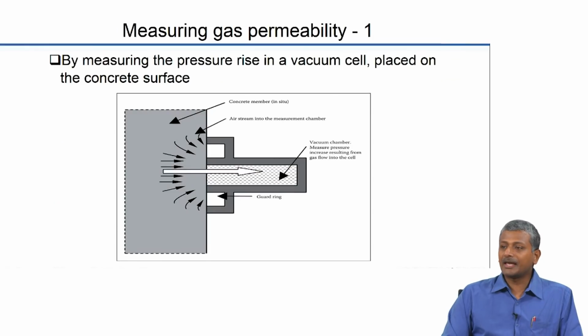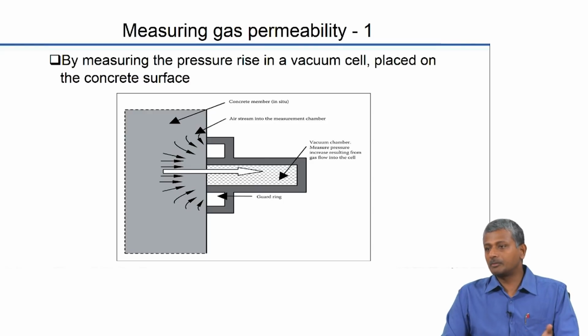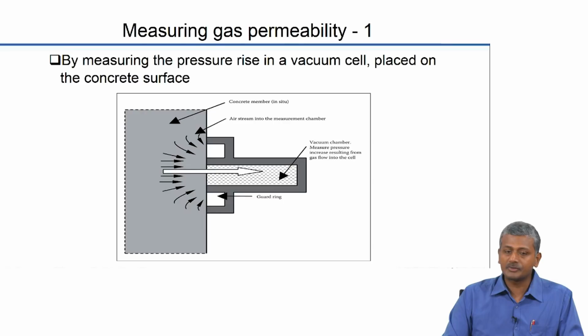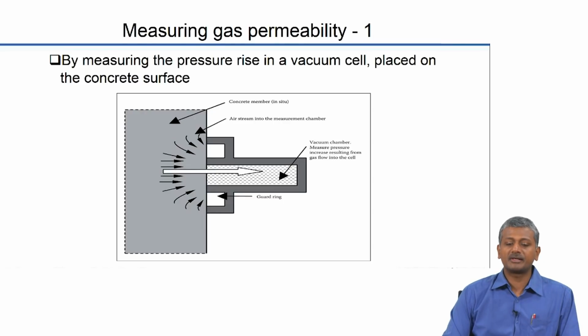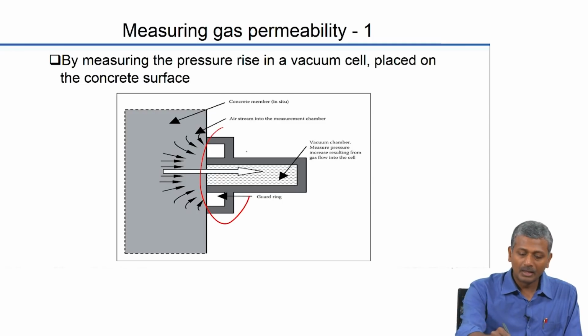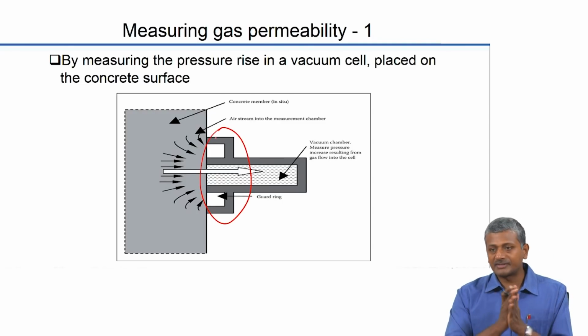Now, gas permeability can be measured in several ways. Okay, water permeability, I talked about two different techniques. So, gas permeability can be done in several ways. One is by measuring the pressure rise in a vacuum cell which is placed on the concrete surface. So, you again have a cell with which you create vacuum and affix it to the concrete surface.